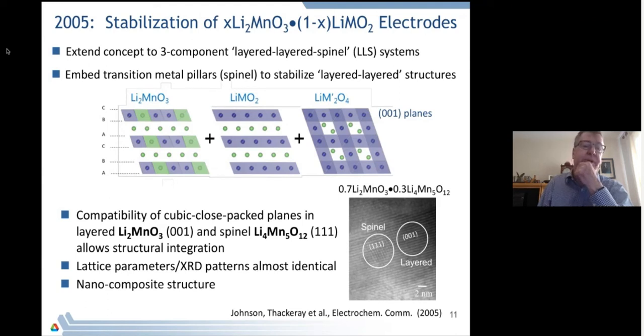And we've looked at the problems, and we extended the concept of using these structurally integrated materials to a three-component system where we introduced some spinel into these structures. And the motivation behind that was to use the spinel as pillars to stabilize layered structures. And we all know that in the spinel structure, 25% of the transition metals are located in the lithium layers. And the compatibility of spinel, Li4Mn5O12, and Li2MnO3 can clearly be seen on the TEM image on the right-hand side, where you can see this beautiful integration between the two components. The reason for that is that the lattice parameters and the X-ray diffraction patterns of these two materials are almost identical, yielding this beautiful nanocomposite structure.